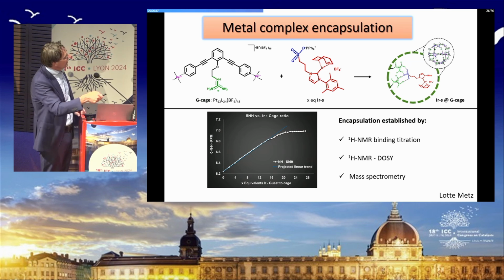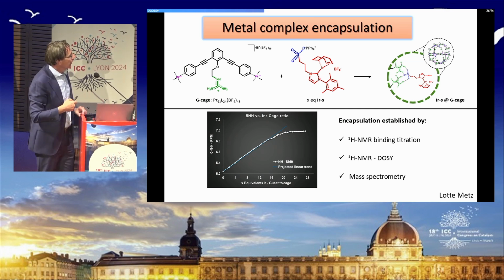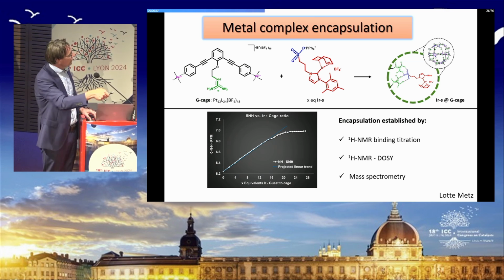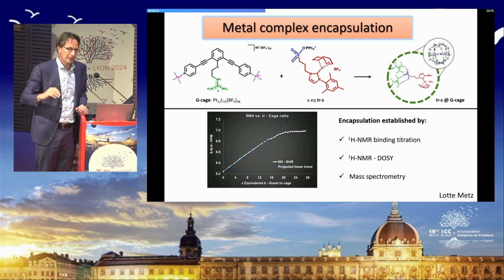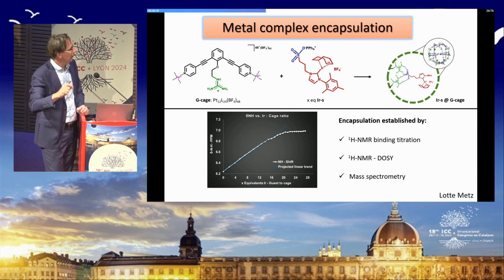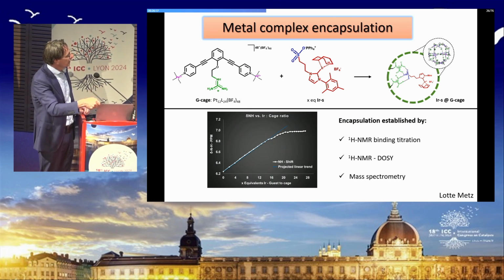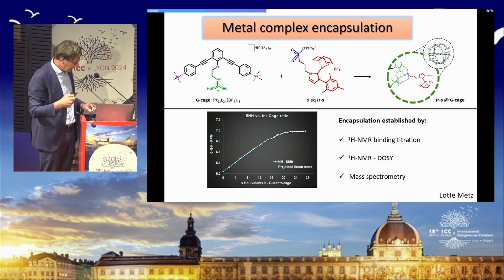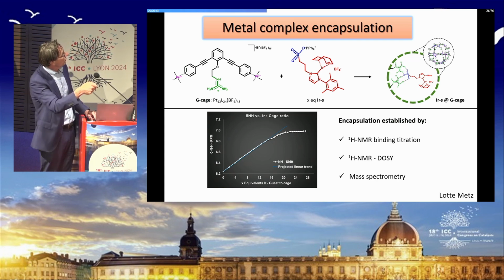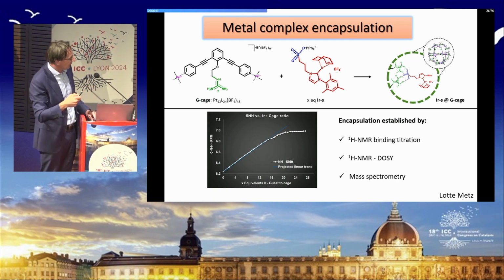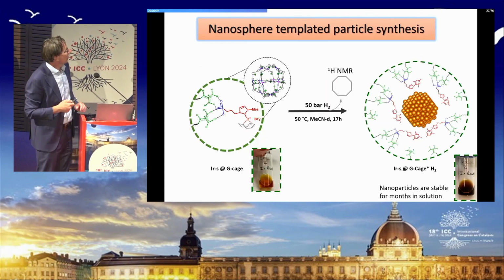So metal encapsulation has been established by an NMR binding titration curve, as you can see here. So up to 24 metal complexes can bind inside. We do NMR DOSY, diffusion ordered spectroscopy, to measure the size of the cage with and without the metal complex. And by mass spec, we can identify these species. So clearly, the iridium complex goes into the cage.